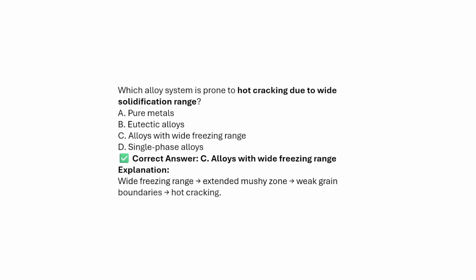So which alloy system is prone to hot cracking due to a wide solidification range? Pure metals, eutectic alloys, alloys with a wide freezing range, and single phase alloys. So the answer will be C, alloys with a wide freezing range. A wide freezing range extends the mushy zone and weak grain boundaries, which results in hot cracking.